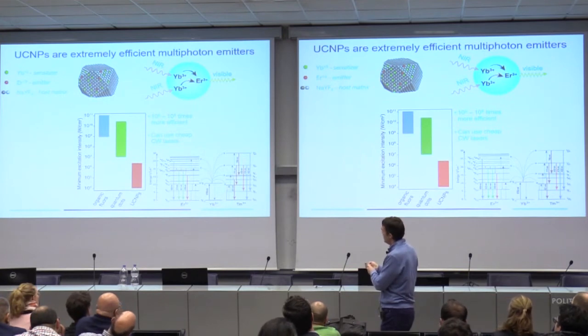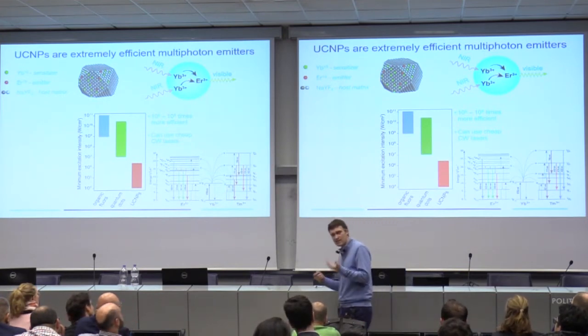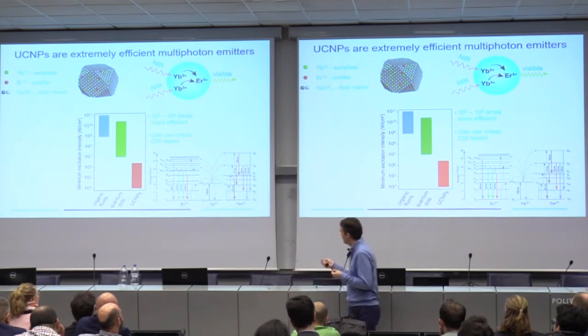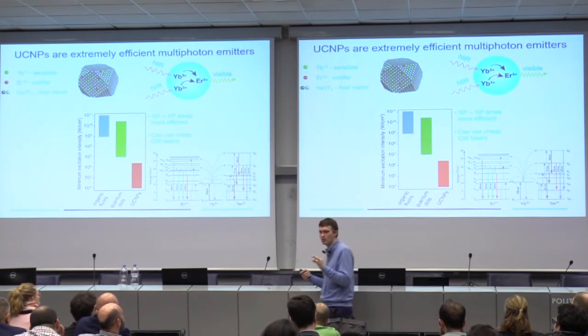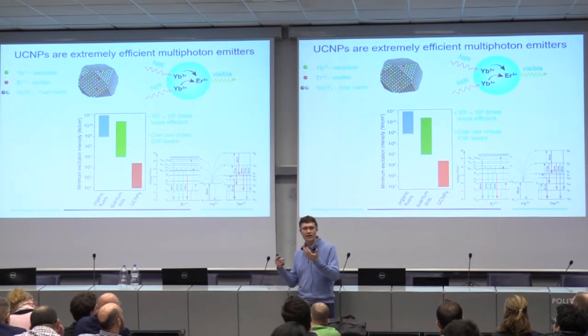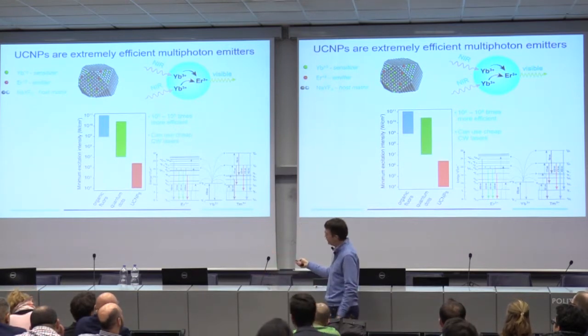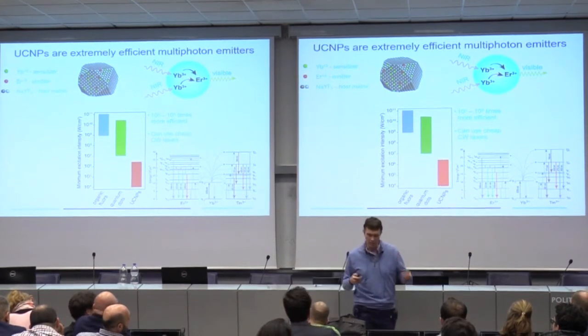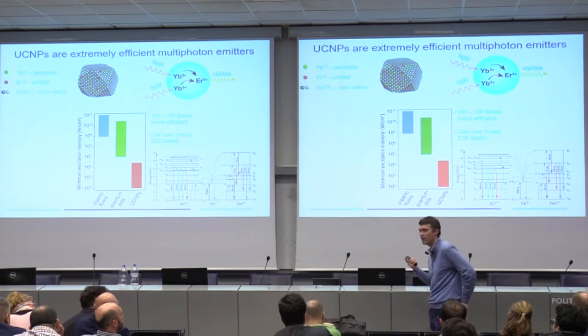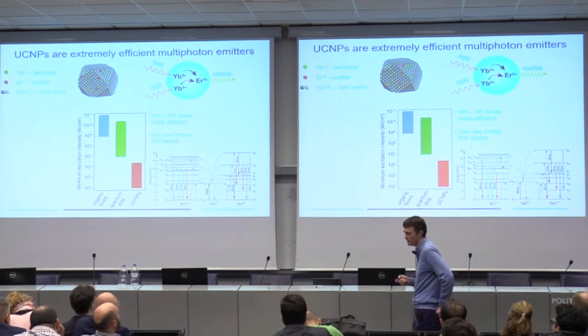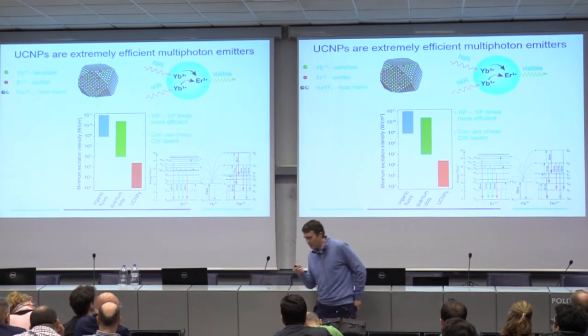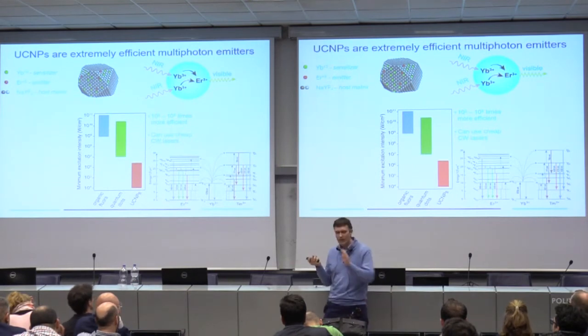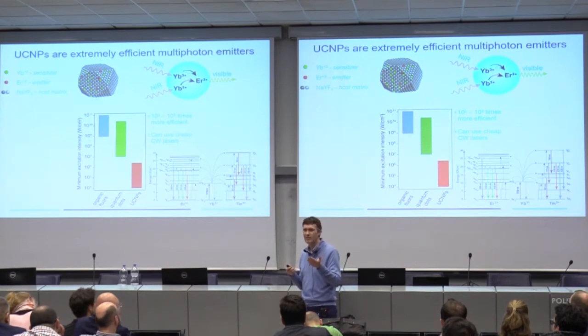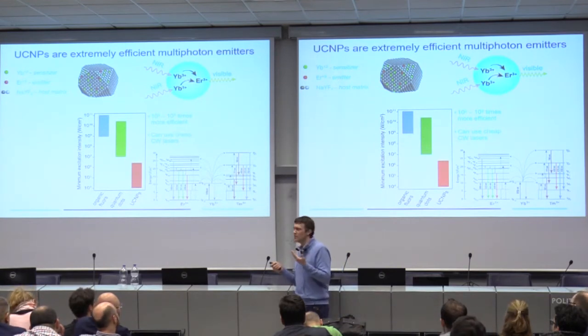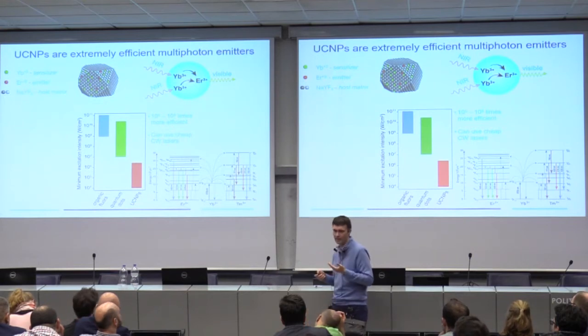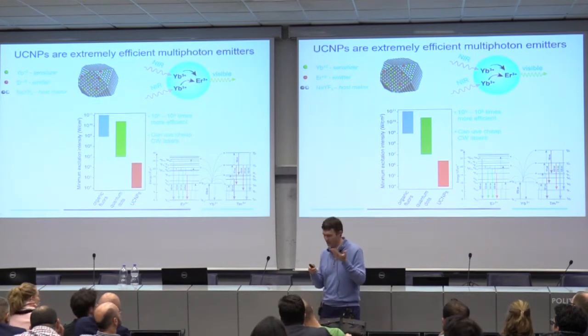Typically, people will use ytterbium, Yb, as a so-called sensitizer. That's because Yb has one excited energy state, and it has about a 10 times larger absorption cross-section. So that absorbs your light, and then it funnels it into the other lanthanides that you use for the emission. You can control, for example, the color of emission just by changing the lanthanide that couples to the ytterbium. But again, it's a double-edged sword. They have very long-lived excited states, but they don't absorb much light. So what we tend to do is pack as many as we can into one particle, at least until other issues start kicking in. So let me tell you about these.